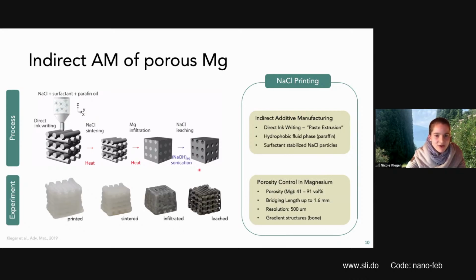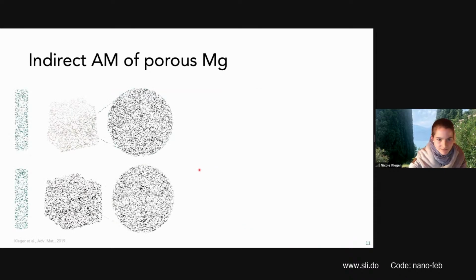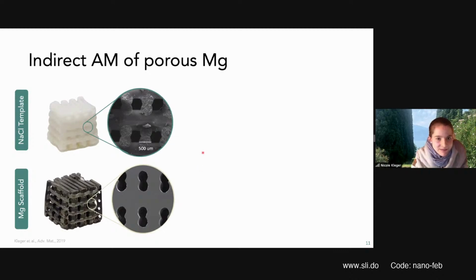So this is how the real samples look like. We are able to reach porosities between 40 and 90% approximately, and the resolution is about 500 microns. This is how the real samples look in the end. So as you see on the top, this is the sodium chloride template. So we have these really round struts. We can stack them, we can put them laterally, however we want them. And they are tuned to about 500 microns because this is the size that osteoblasts, so bone cells, really like. And on the bottom, you see the transfer to the magnesium scaffolds with the circular holes as well.